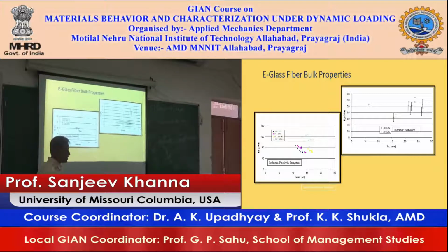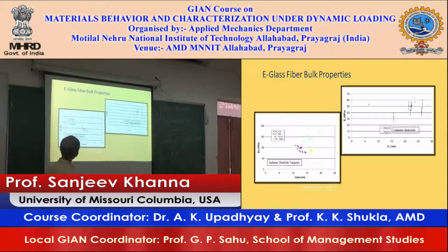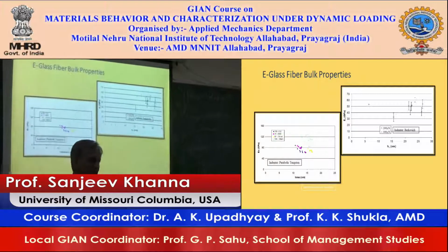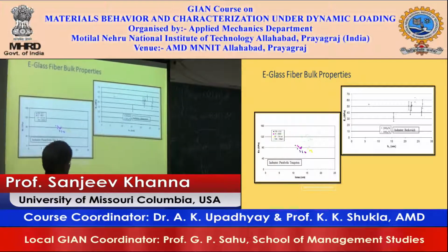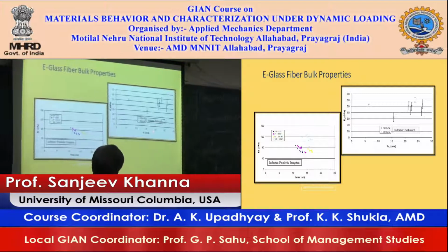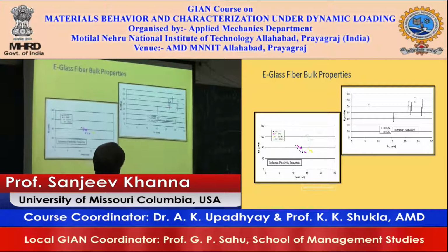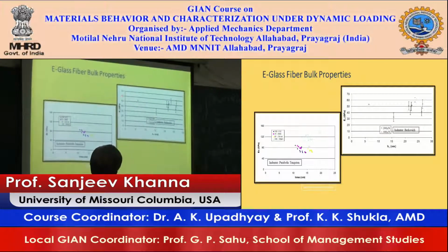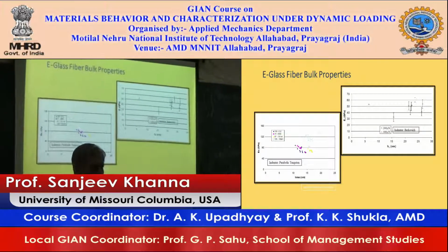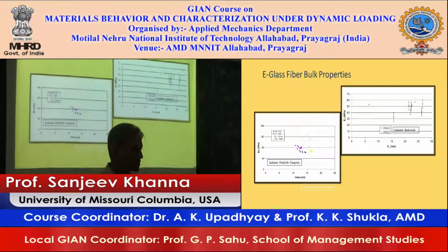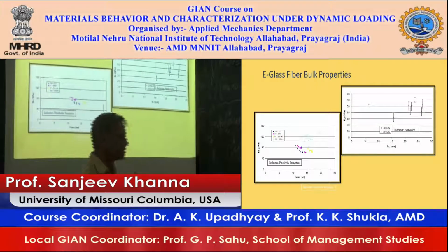If we go to higher loads and bigger indents, we get up to about 120, which is obviously not right. With the Berkovich tip, even for high loads, we get better values, about 50, but that's much lower than the elastic modulus of glass, which is about 72, 75.